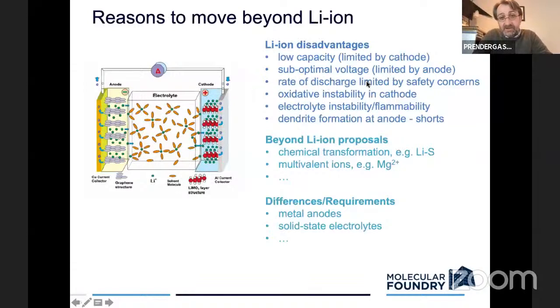The rate of discharge is limited because there's some safety concerns. If you discharge too quickly, you might start burning the electrolyte. There's some instability, and then the famous dendrite formation where lithium fingers extend from the left-hand side to the right, short the cell, and cause fires. So some beyond lithium-ion proposals would be chemical transformations. So you start with a material like sulfur and convert it to lithium sulfide. We'll talk about that at the end of this talk.